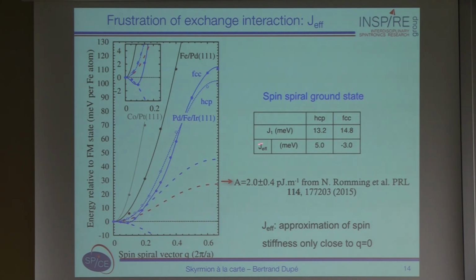So actually, we came up with this J effective concept, where we said, okay, let's fit our dispersion curve only close to the gamma point, get one parameter that we call J effective, and let's see if it has any consequences on the energy barrier or temperature dependence. So we did it for these two systems here, palladium, iron, iridium 111. And you see that for the HCP palladium overlayer, the J effective, which is obtained from DFT and from experiment, is actually very close.